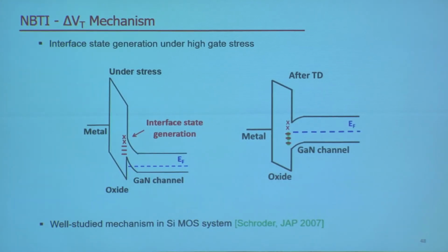And what we believe is happening is the interface state generation under high negative gate bias stress, where defects can be generated at the aluminum oxide gallium nitride interface, and after the removal of stress, they are left behind and not recoverable. So this is a very well-studied mechanism in silicon MOSFET systems, and there is a lot of reference on the web that you will be able to find.